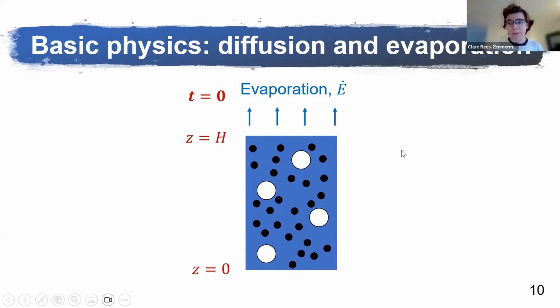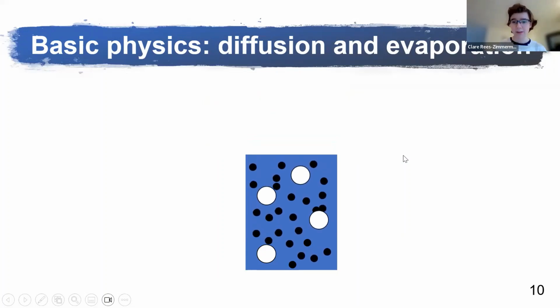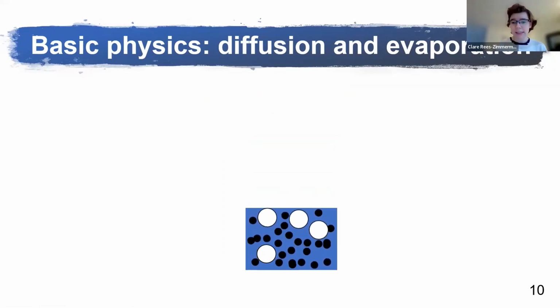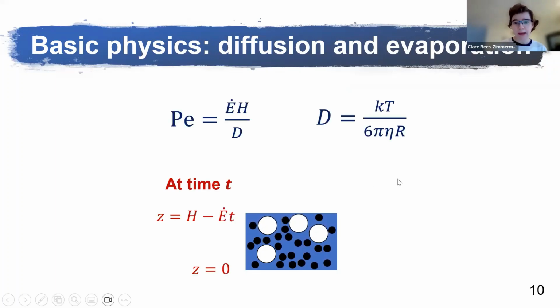So on this slide, I have an imagined animation of a process where I've only modeled diffusion and evaporation. Initially, the top surface is at height h, but the top surface descends over time, and the particles therefore become closer together until they would become close packed. There's a playoff here between diffusion and evaporation. Particles which can't diffuse fast enough would be trapped by the descending top surface, whereas particles which can diffuse faster can spread further down the film.